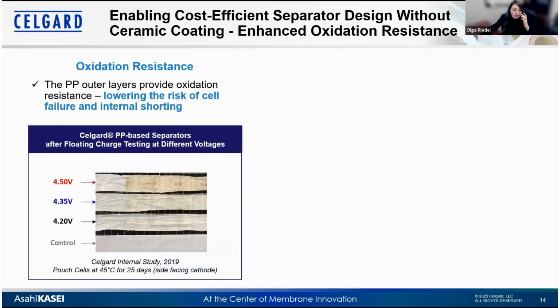So even though I briefly mentioned that Celgard has actually pioneered the ceramic coatings as the inventor with our original 568 patent, PP enables us to also use base film only. This is due to, especially in ESS applications, where a lot of systems use LFP cathodes, but this is mainly due to the high oxidation stability of polypropylene in electrochemical systems. So this is important since ESS cells operate over decades and reliability is key, but also enabling the usage of base films without a ceramic coating enables more cost-efficient cell designs.